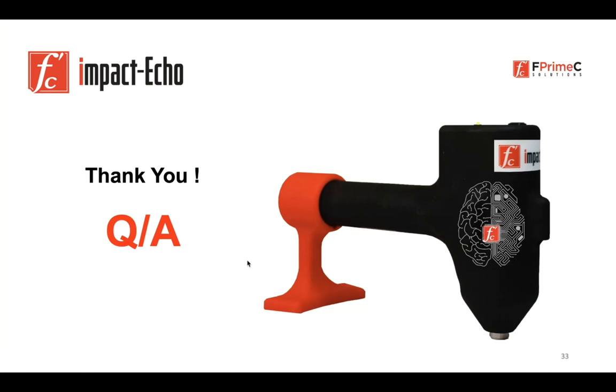Okay, and then another question is, what kind of sensor do you use? What is the highest frequency we can record for shallow delamination? For our Impact Echo machine, we are good to measure shallow thickness from around 50 millimeters or 70 millimeters up to 700 millimeters. That is the range we are covering. For that, we need to rely on frequency over 20 kilohertz or 25 kilohertz.